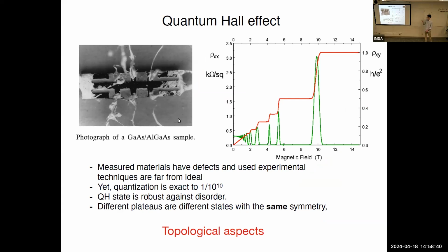This is again those plateaus, and just so that people who don't do experiments can appreciate it even more, I'm going to show the real Hall bar with how it's actually done. You can see how messy those electrodes are, and these samples never are perfectly clean. They always have disorder, but yet these plateaus are quantized to the level of 1 part in 10 to the power of 10, which is ridiculously precise. So one can easily say that these systems are very robust against all sorts of disorder and experimental non-idealities, because you see there are a lot of those non-idealities.